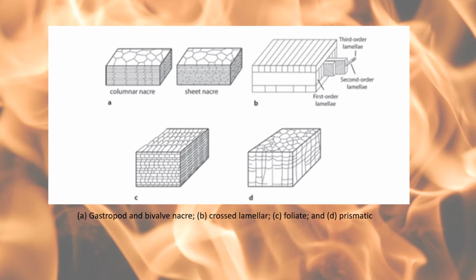B is crossed lamellar microstructure, which is present in a lot of the evolved gastropod and bivalve families, what people would tend to think of as clams or cockles, whelks, and so on. And here you've got these long laths, and they're arranged at 45-degree angles to each other, roughly. So it has a very low proportion of organics, especially relative to, well, actually all of the other microstructures I'm showing on this diagram. You tend to get a very rough fracture with it. You can't cleave straight through because of the way it's put together. So it's a very robust, resilient microstructure.